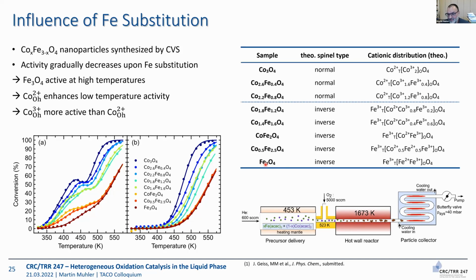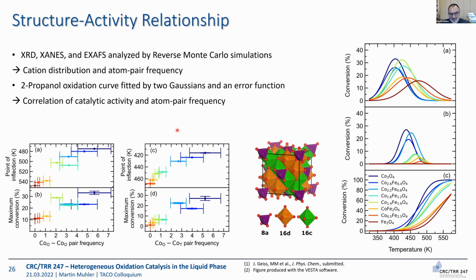So that is magnetite, inverse spinel, and then you fill in more and more and more cobalt. Here is an important step because here you get for the first time then cobalt 2+ in tetrahedral sites, and then here you're in the regime of the normal spinel. And you see again this sequence, Co3O4 is actually the most active catalyst, very systematically. If you add iron, the low temperature channel goes down, also the high temperature channel goes down. And these samples allowed a very special way of structural analysis, a reverse Monte Carlo simulation of this structural data set